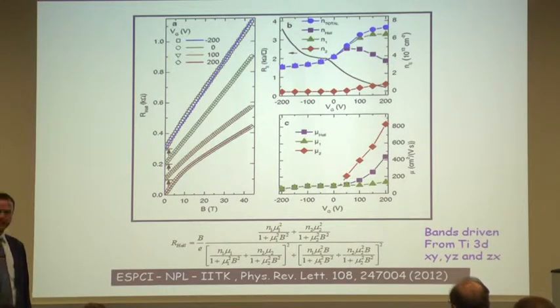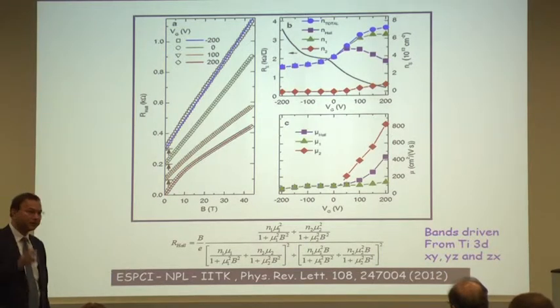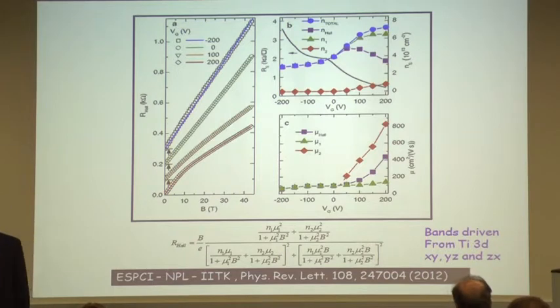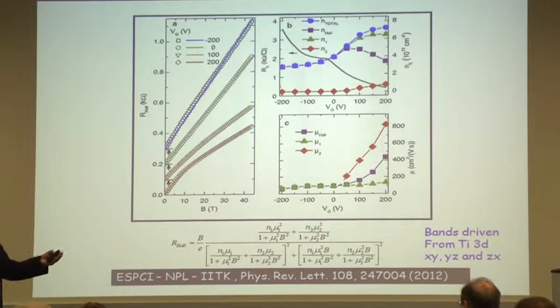And these two types of carriers come as you apply the gate voltage. It has something to do with the band structure, the titanium T2G states. So if you look at the dispersion of these bands, XY, YZ, and ZX, it turns out that initially you have XY. You start putting carriers in XY, which has very little dispersion. These electrons are very sluggish. The mobilities are low. And if you keep on applying more and more gate voltage, then you start pulling these two down, which are almost degenerate, and you start putting carriers in those bands, and these bands are much more dispersed, so the mobility is much higher.